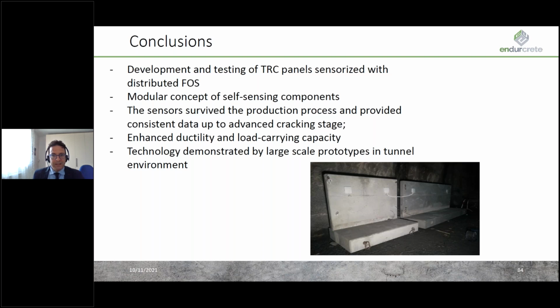We developed and tested textile reinforced concrete panels sensorized with distributed fiber optic sensors, with the final goal to develop a modular concept of self-sensing components. We found that the sensors survived the production process and provided consistent data up to advanced cracking stage. Also, the TRC solution provided enhanced ductility and load carrying capacity. And finally, we demonstrated this technology by large-scale prototypes in real tunnel environment.